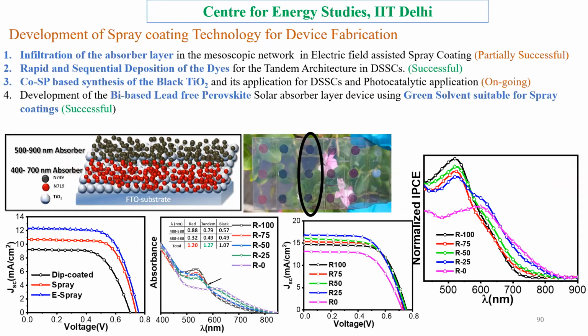Tandem solar cells have nowadays attracted very much attention, like how I use a plasmonic to enhance the light absorption capacity. The same way I can use this tandem device, taking two different dyes. One dye is absorbing the 400 to 700 nanometer region, and another dye is absorbing the 500 to 900 nanometer region. So now I can absorb 400 to 900 nanometer, because every dye has a limitation. It can have a particular absorption region only. So I can now use two different dyes.